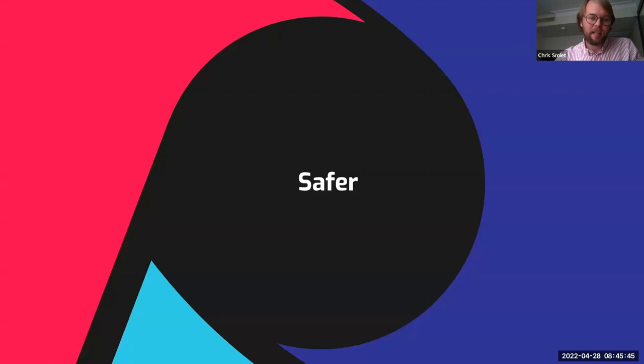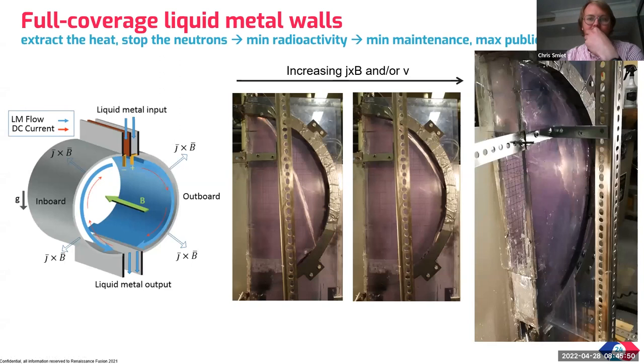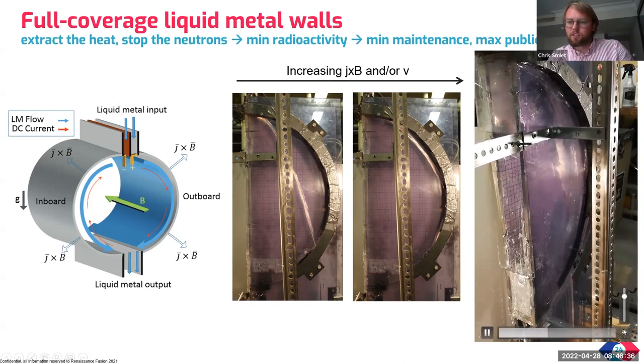Now, the last step is to make it safer as well, so to stop the neutrons from the DT reactions from causing damage. Here, our simplified manufacturing approach helps us a lot, again, because it's much easier to stabilize a flow of a liquid metal against a cylindrical substrate. This is something that, in fact, we have even done. This is an experiment that Francesco performed in Colombia with magnets around the side here and a flow of galinstan. That's not lithium, but you can translate the parameters of one equation to an equivalent thickness of lithium. And turning on currents can cause the Lorentz force to stabilize the flow against the wall.